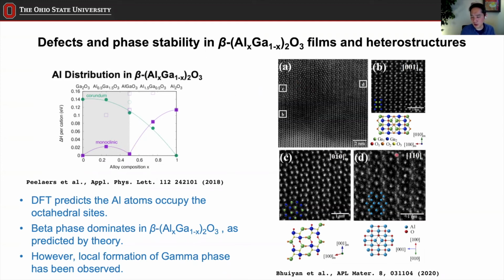But then what happened? What people have noticed is that locally, in a very local region like this, there's something else happening, like this one, for example, right? So this is not either monoclinic or corundum, but it's something else that people didn't recognize initially. But later we figured that this is actually a formation of gamma phase that I showed you a few slides ago. So in fact, the gamma phase formation is very common. For some reason, gamma phase is likely to form, especially in aluminum gallium oxide. Maybe it has something to do with the strain because of the lattice mismatch. But the gamma phase formation is pretty commonly observed in this type of growth.